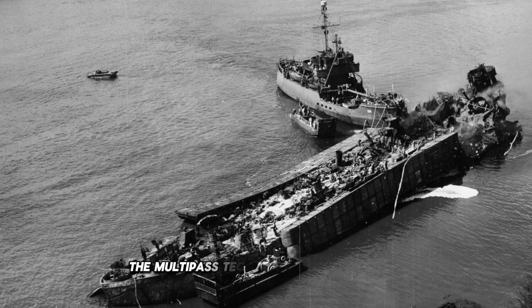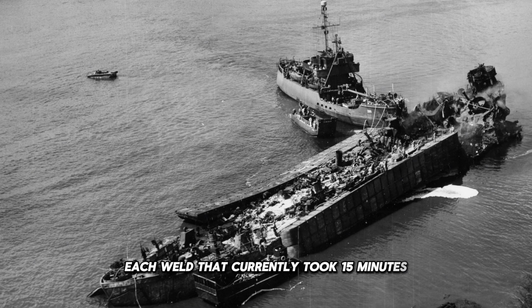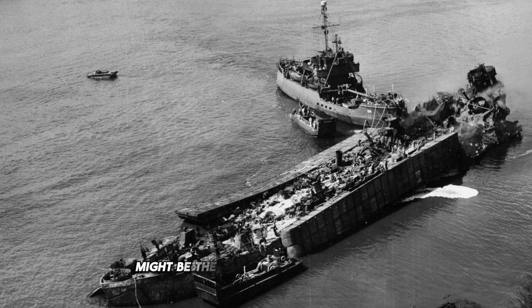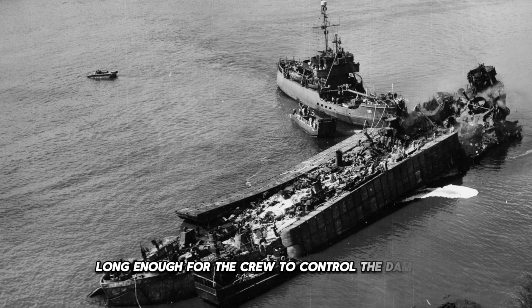The multi-pass technique would cost time. Each weld that currently took 15 minutes would take 45 minutes. But those 45 minutes might be the difference between an LST sinking in 4 minutes versus staying afloat long enough for the crew to control the damage.